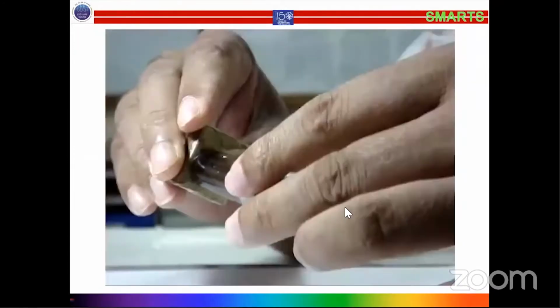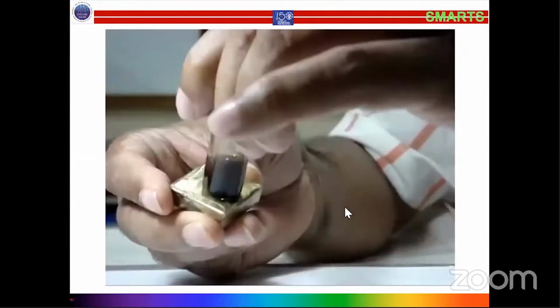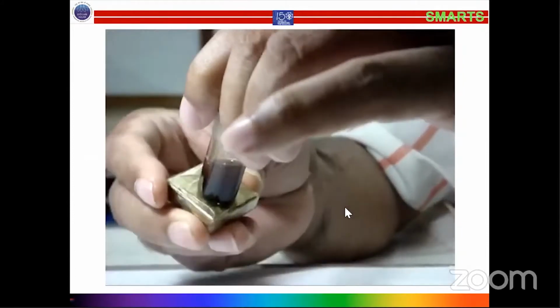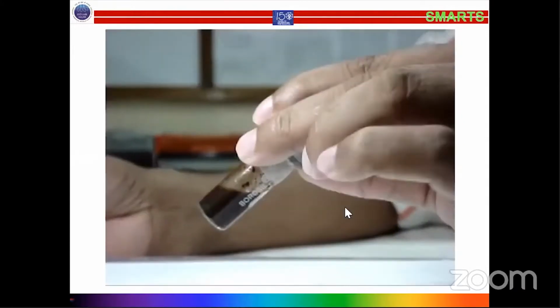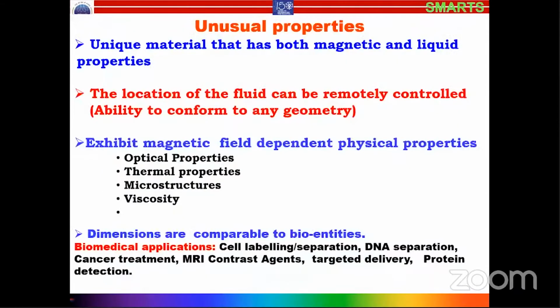The liquid is separated from these particles, whereas in the other case, the liquid is not separating from the particles. So you provide mechanical energy to stabilize such particles. Even then, you provide mechanical agitation, it may get dispersed in the fluid, but when you apply a strong magnetic field, then again they will cluster because they are like tiny magnets. So this is a unique material that has both magnetic and liquid properties. Now you have seen in the movie, the location of the fluid can be remotely controlled, and the fluid has an ability to conform to any geometry.